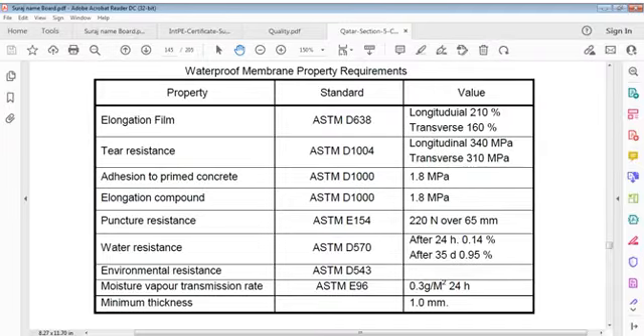So besides, sorry, this is about the elongation of the film. It says that elongation is ASTM D638, longitudinal 210% and transverse 160%. It's quite good. You can expand 210% lengthwise and 160% transverse-wise. Tear resistance is ASTM D1004, longitudinal 340 MPa and transverse 310 MPa.